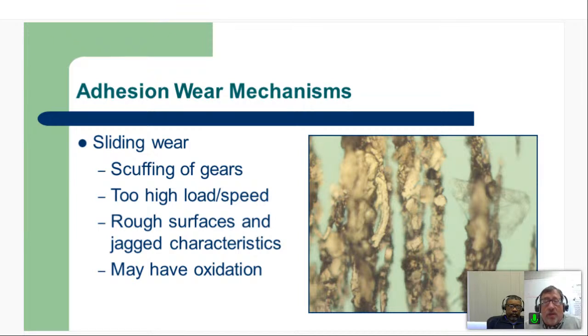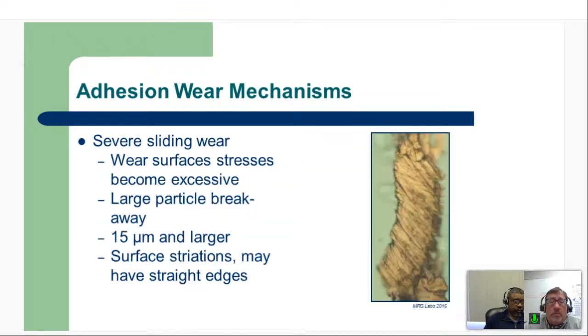And then you get sliding wear, the larger particles where you get long lines on there. It's a thicker particle, but you see lines, or what we call striation, where they are rubbing one surface against the other. And they might be rough or jagged. They may even have oxidation. They might change color because of the temperatures they are subjected to as this mechanism is forming these larger particles.